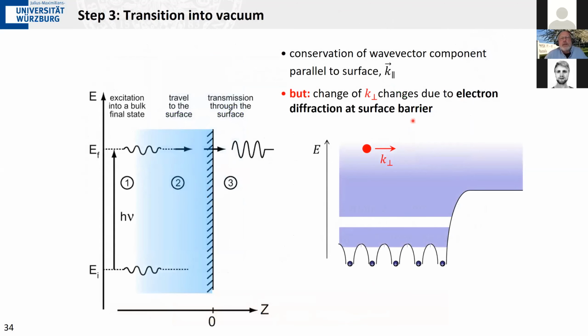And finally, and that is important then if you want to do momentum dependence of your photoelectron distribution, if you want to map out band structures, you have to take into account what happens when the electron transits through the surface. Parallel to the surface, we still maintain periodic symmetries. You have a certain crystalline order here in your sample, and trivially, the vacuum has the same order. If you go by a certain lattice constant, nothing changes in the vacuum, and therefore k parallel, the component of the momentum of the photoelectron parallel to the surface, is conserved and does not change as the electron goes through the surface. However, the vertical component, k perpendicular, that changes due to electron diffraction at the surface.